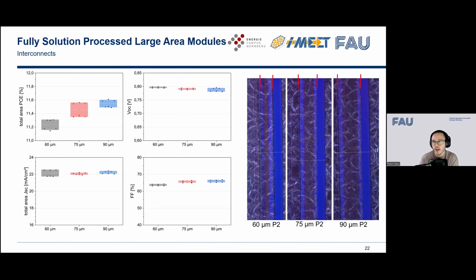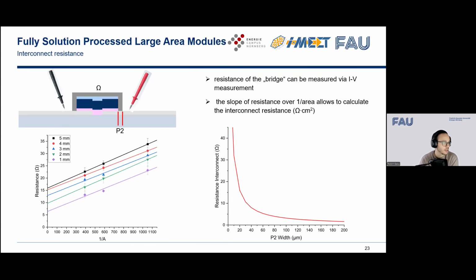So then we had to know, okay, what is the optimal P2 width that we can use for our devices on 200 square centimeters? And for that, we did a more or less bridge setup with a P2 line in between ITO glass. Then we put the stack on top and basically had a P2 bridge in between. And then you just measure the resistance with 2 pins on the left and the right-hand side. And you basically have the interconnect twice, so you have to divide the resistance that you get out of the IV curve by 2.